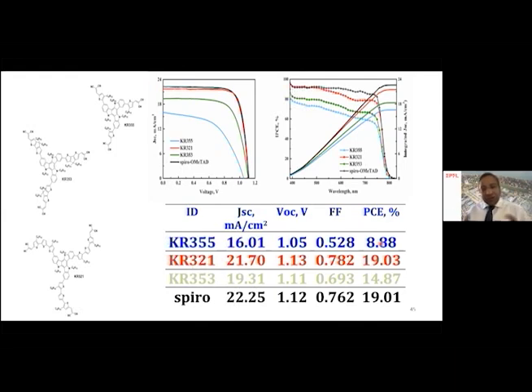So here also there is a take-home message that we need a certain number of thiophene groups to interact with the perovskite layer to give enhanced efficiency. Compared to two thiophene, three thiophene is better, and one thiophene is even lower.